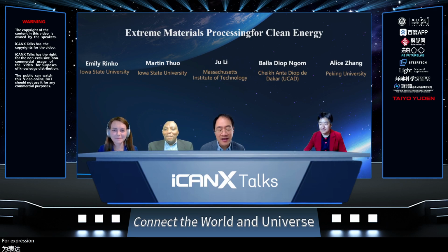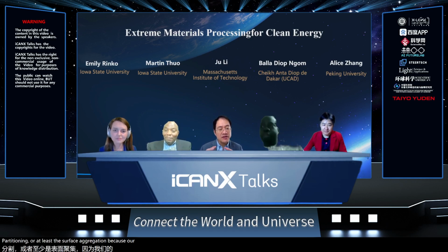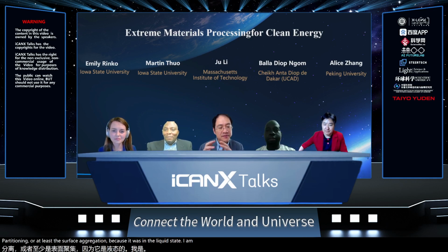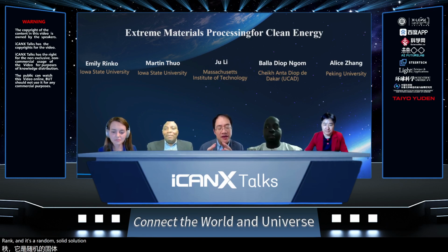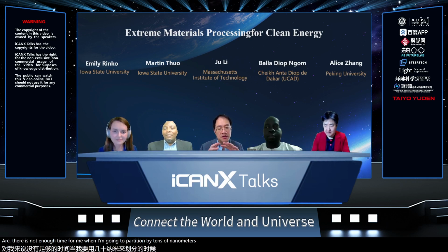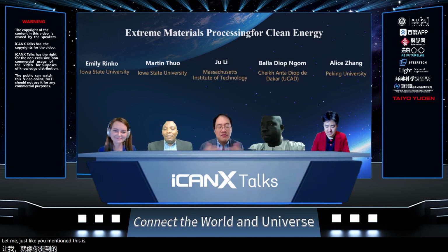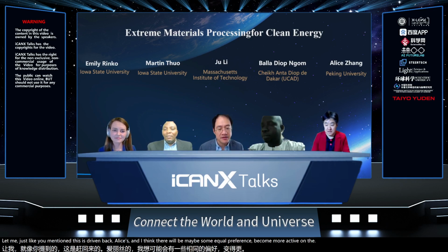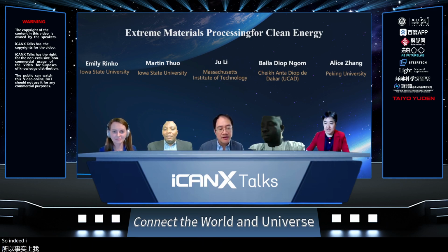Great question. Yeah, I think there should be some partitioning or at least the surface segregation, because it was in the liquid state. It's a random solid solution liquid. And then our theory is that because of the rapid quench, there is not enough time for nickel and gold to partition by tens of nanometers. But certainly, just like you mentioned, this is driven by catalysis, and I think there will be maybe some nickel preference because nickel is more active on the surface. So indeed, I would say there is a gradation.